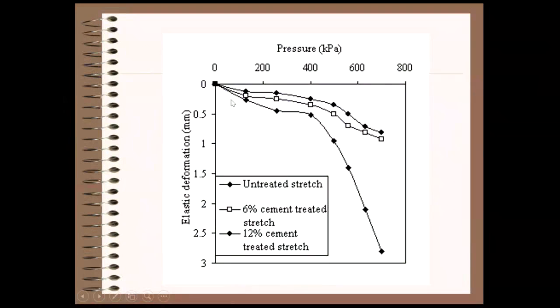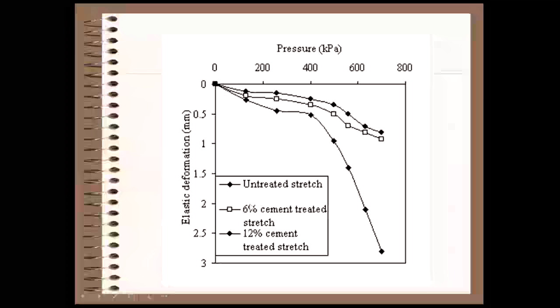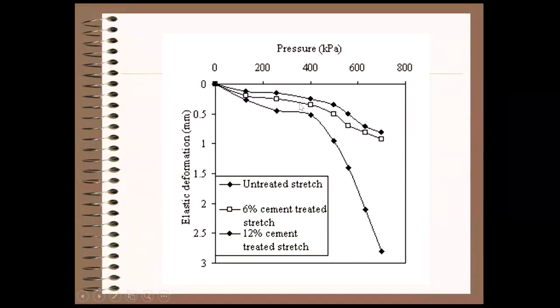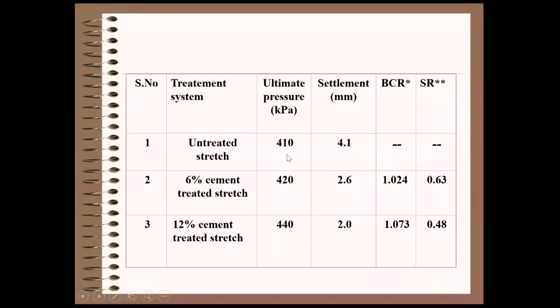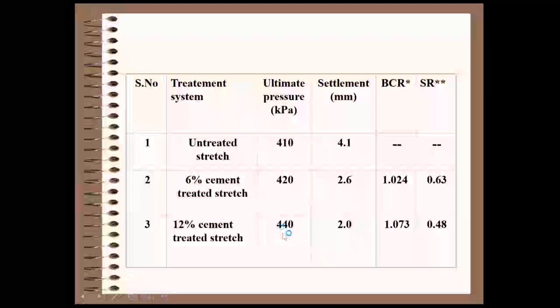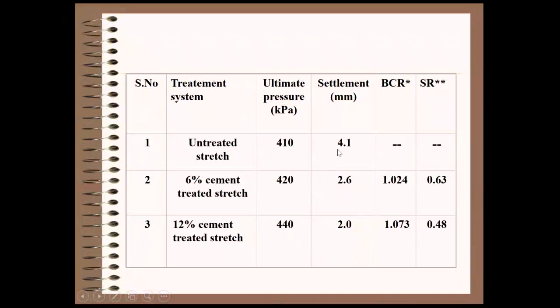Then elastic deformation is very important to understand the pavement life. That also significantly reduced when cement stabilized. So this indicates high or increased life of the pavement. And another very important point, bearing capacity people normally use predominantly in engineering practice, but that understanding we have to be very clear. You see, without stabilization or with stabilization, the bearing capacity is not changed very much, right? Interesting. Settlements are changed. This is important. That means in the case of pavement engineering, whatever that aggregate soil, everything when they are a little dry, bearing capacity wise, everything will be satisfied.